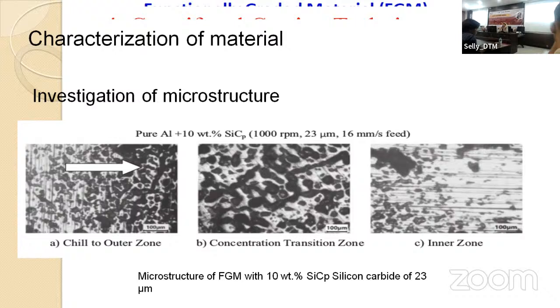Look at that. It's the outer zone and it's the inner zone. I want to show you different sizes of the silicon carbide added material. This example belongs to the 23 micrometer one. What about the chill zone? Chill zone means the nearest area to the mold wall, so it chills fast.